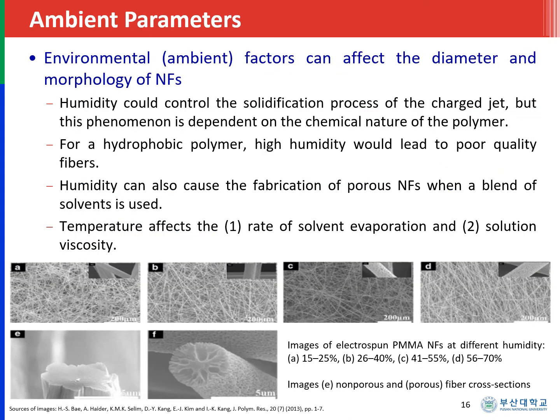The last group of electrospinning variables which also influence the diameter and morphology of nanofibers is ambient parameters. Humidity could control the solidification process of the charged jet, but this solidification is dependent on the chemical nature of the polymer. When you say chemical nature, the polymer could either be hydrophobic or hydrophilic. If the polymer is hydrophobic and there is high humidity, then during electrospinning, you will produce poor quality fibers, beaded and unspun droplets. Humidity can also cause the fabrication of porous nanofibers when you are using a blend of solvents in the dissolution of your polymer.